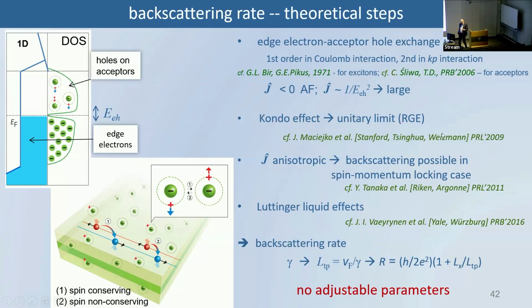And if you have Kondo effect, it means that this acceptor, which has a spin, can attract the cloud of electrons from this edge states and form a bound state. And this gives rise to very strong scattering, actually. This gives rise to scattering which has the so-called unitary limit. And then you have to take into account spin-orbit interactions, so that you have anisotropic exchange coupling. You have to take into account interaction, because in the one-dimensional case, interaction between electrons is very large. And then you can calculate this backscattering rate.